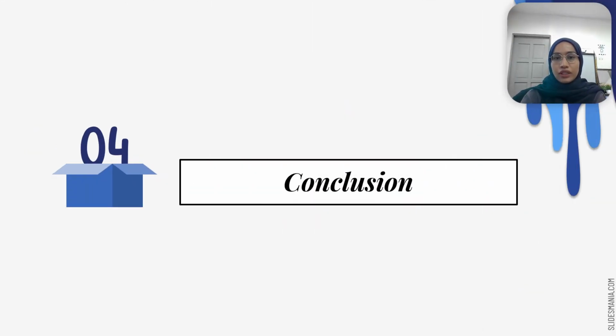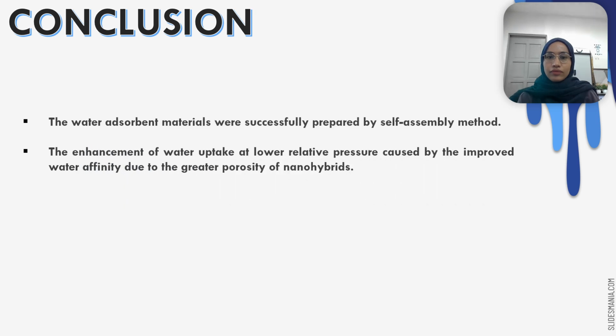Okay, here comes the conclusion of this presentation. We can conclude that the water adsorbent materials were successfully prepared by a really simple method, which is the self-assembly method. And the enhancement of water uptake, especially at a lower relative pressure, is mainly caused by the improvement of the water affinity with the greater porosity upon hybridization between the MOF and the TiO2 nanosheets.